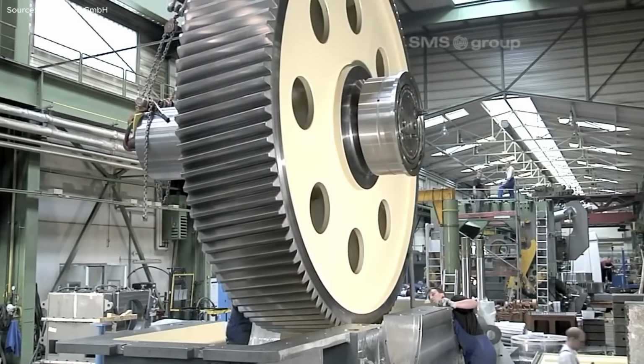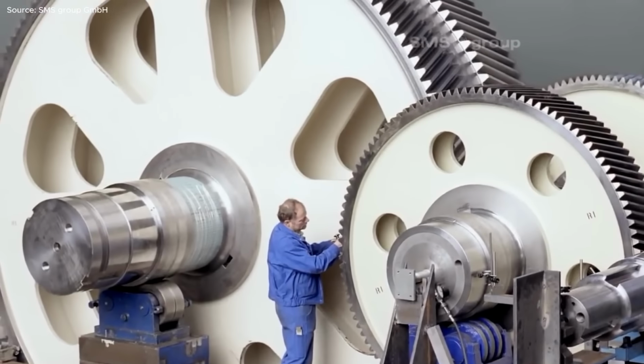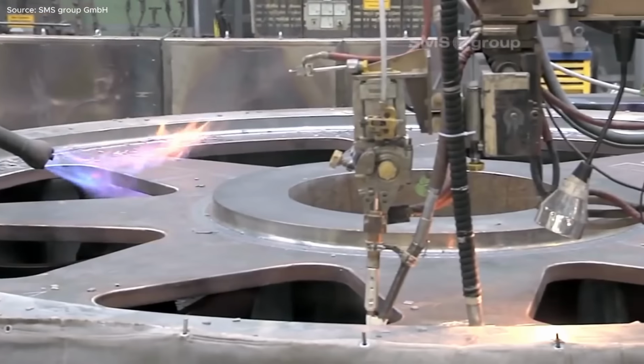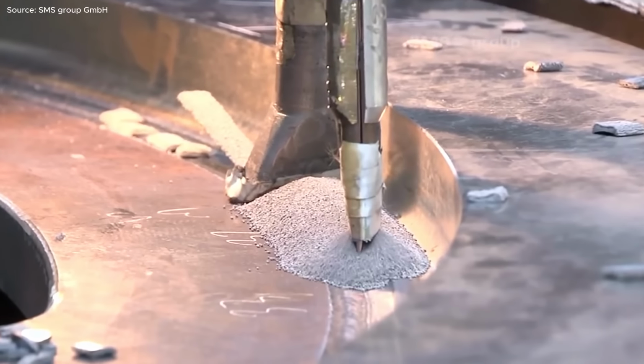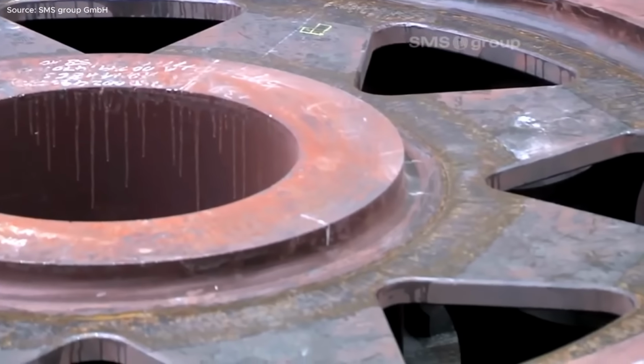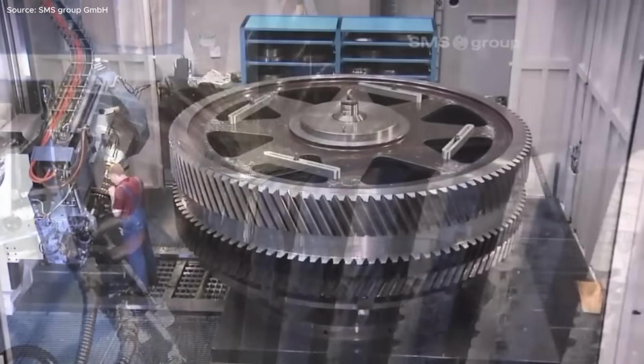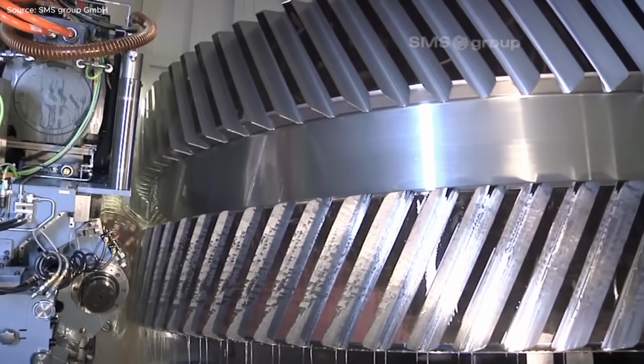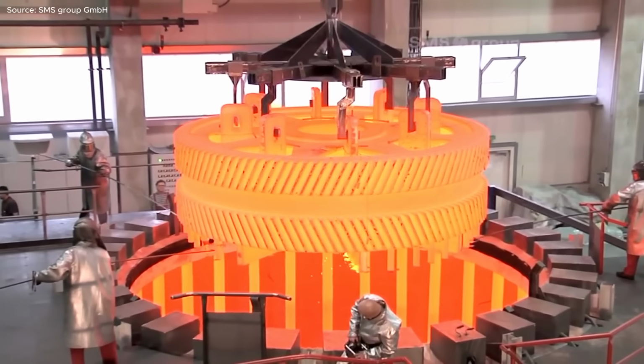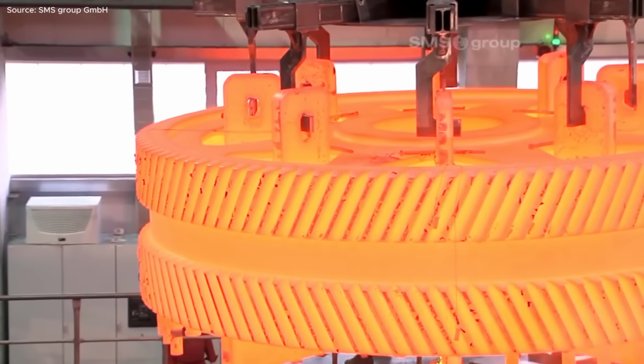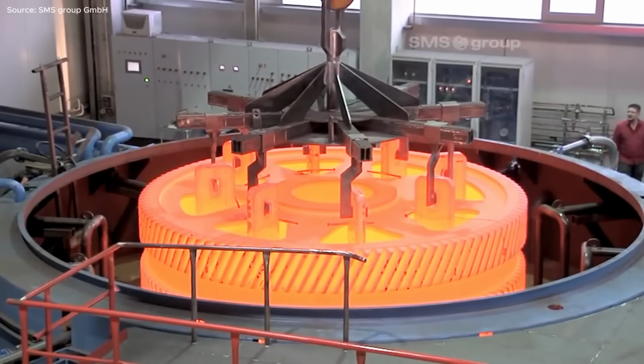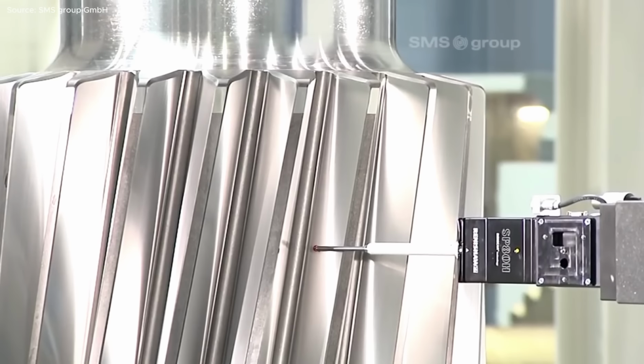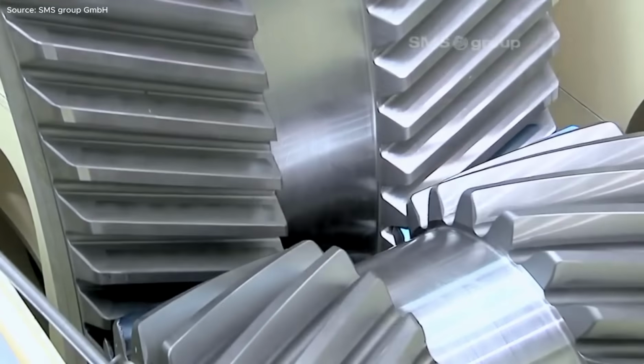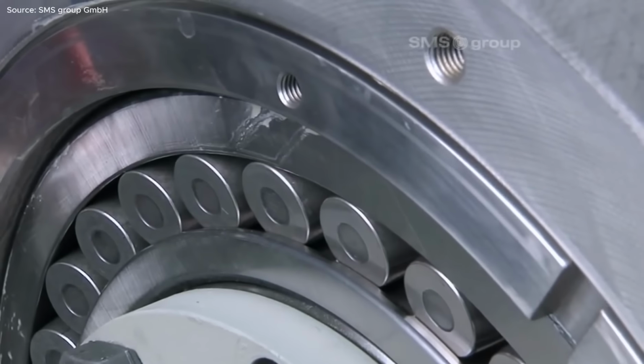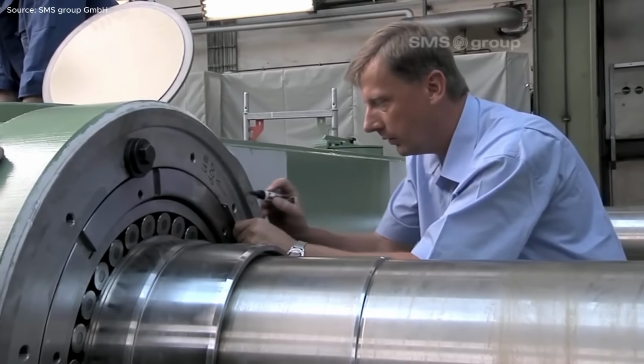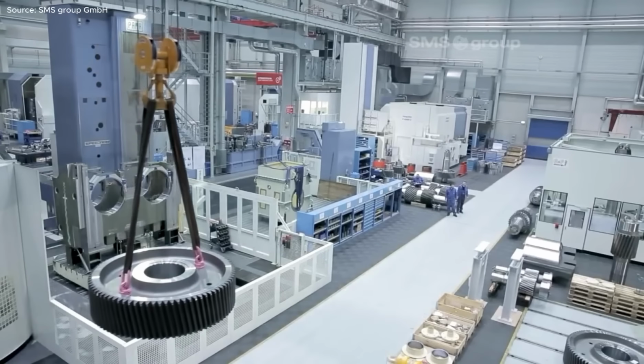Once welded, each unit undergoes heat treatment and stress relief annealing to eliminate internal tension, guaranteeing dimensional stability. The gear teeth are precisely milled on CNC gear cutting machines capable of handling diameters up to 6 meters and modules up to 40. After machining, the gears are case-hardened for wear resistance and subjected to ultrasonic testing to detect even microscopic flaws. Grinding on a profile grinder refines the tooth geometry to within microns, followed by 3D laser measurement and computer-aided adjustment of contact patterns. Every housing, bearing, and shaft is manufactured and pre-assembled to achieve seamless torque transfer under extreme loads.